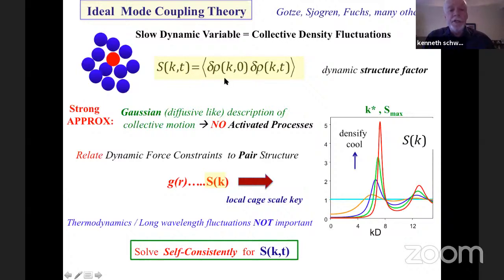Now, there are multiple approximations in the mode coupling theory, as there are in all theories, but the strongest one, in my opinion, is a Gaussian or diffusive-like description of collective motion. The consequence is that you get a closed equation for the dynamic structure factor, but you've given up the ability to a priori predict non-Gaussian processes like activated hopping. Having said that, the beauty of the approach is that you can relate dynamic forces and their constraints to the pair structure. So if you know the pair structure in real space, or technically generally in Fourier space, here's the structure factor, then as you cool the liquid, you have more and more correlation locally, and you can predict dynamics.